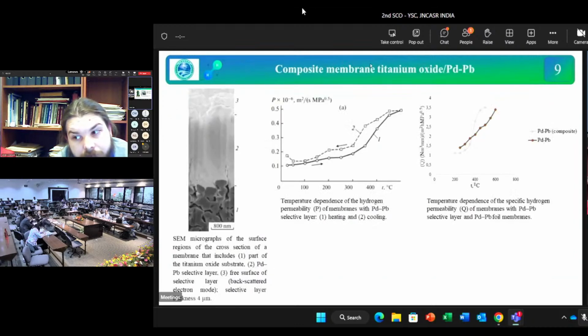To increase the performance of filtering elements, the hydrogen flow is inversely related to the membrane thickness, and to save palladium, it is necessary to decrease the membrane thickness. A composite membrane, with a function layer of four microns in thickness, was designed in the Baikov Institute of Metallurgy and Material Sciences, Russian Academy of Sciences.